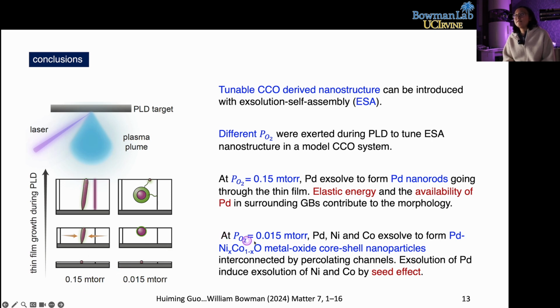At 0.015 millitorr, you can see the palladium, nickel, and cobalt will form the palladium-nickel-cobalt oxide core-shell nanoparticles. These nanoparticles are interconnected by percolating channels. We find through the FFT analysis that the palladium exsolution growth will trigger the exsolution of the nickel and cobalt to form an oxide shell around the palladium, forming core-shell nanoparticles by the seed effect.